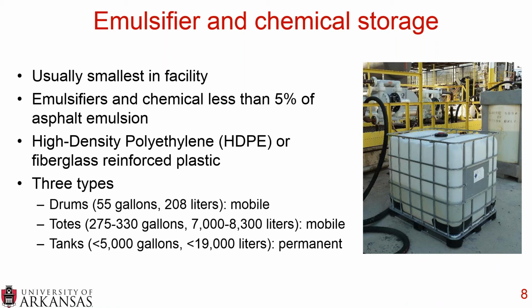So if you use one type of emulsifier or one type of chemical, for example, cationic asphalt emulsions often use hydrochloric acid or HCl as an additional chemical. So if you make a lot of cationic asphalt emulsions, you may have a tank of hydrochloric acid on site. Now, because it's not used in a lot of quantity, they're usually less than 5,000 gallon tanks, so relatively small, but those are permanent. You're not going to move those around.